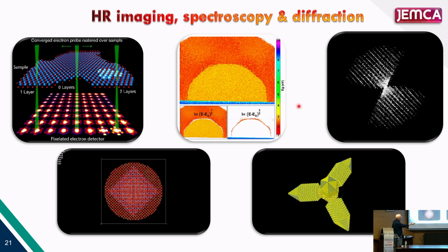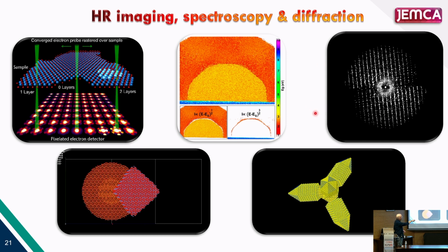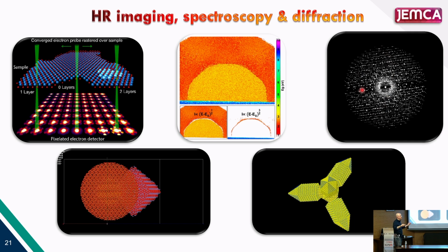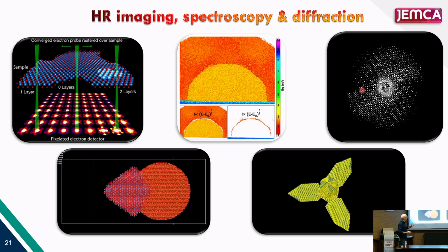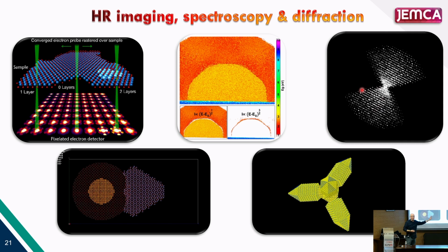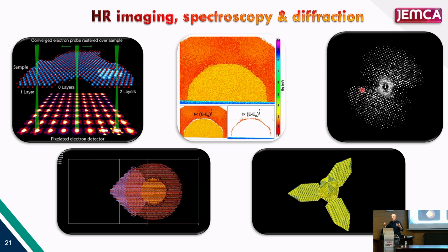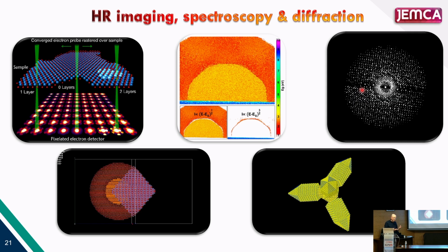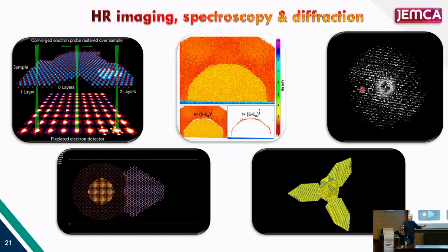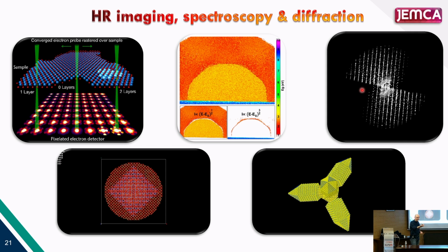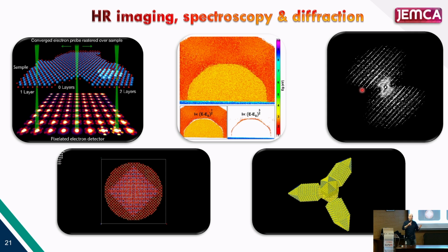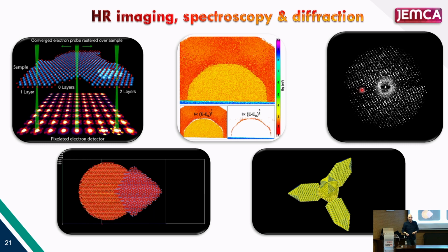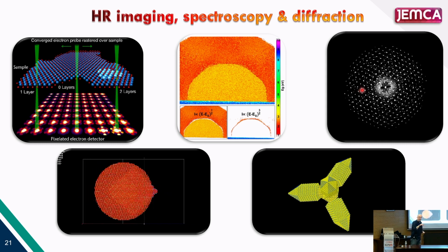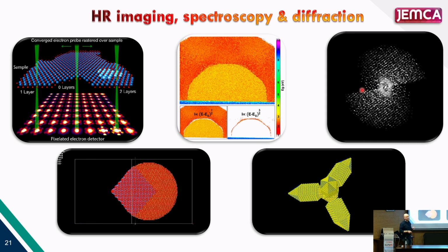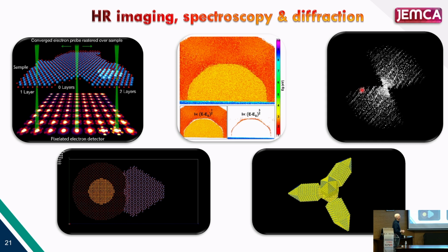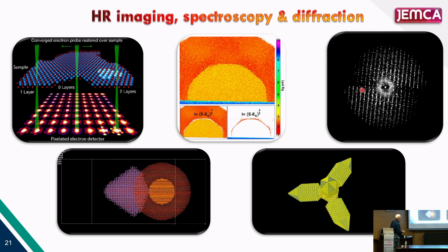So you can go to the reciprocal space and get 3D diffraction maps in 3D and understand really the structures, but this can be done in a single nanoparticle. So you don't need anymore to go to XRD and get the whole material, because if the material is pure, that is amazing. You can detect in average what you have, but imagine you have a single nanoparticle, or maybe not a nanoparticle, but you have an inclusion inside your material. So you can go with your beam, go right there, and with a small tomography, you can get a 3D reconstruction of the structure of this small, I don't know, precipitate or a small nanoparticle.